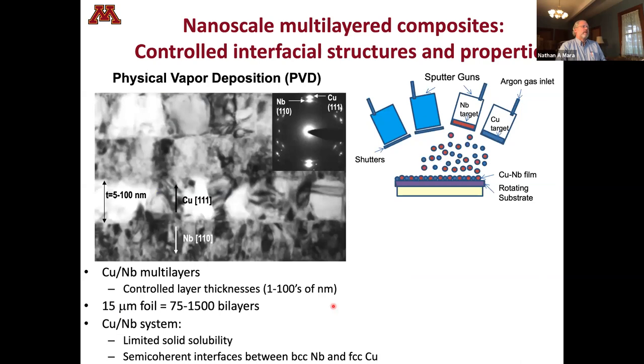So a little bit about how we make these. Let's talk about physical vapor deposited material first. These are made in a sputter chamber, so magnetron sputtering. You take a rotating substrate, you can deposit either copper or niobium, and you build up your structure one layer at a time. So you grow niobium, and you grow copper, and you grow niobium, and you grow copper. These are polycrystalline foils. So you do have grain boundaries that you can see within the structure. We have this kind of columnar, known as a bamboo morphology, where the out-of-plane direction is similar between all of these different columns, but there is an in-plane rotation between them. So that's what gives you your polycrystalline feature.